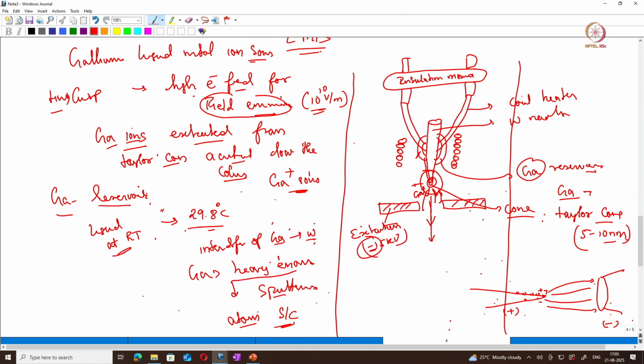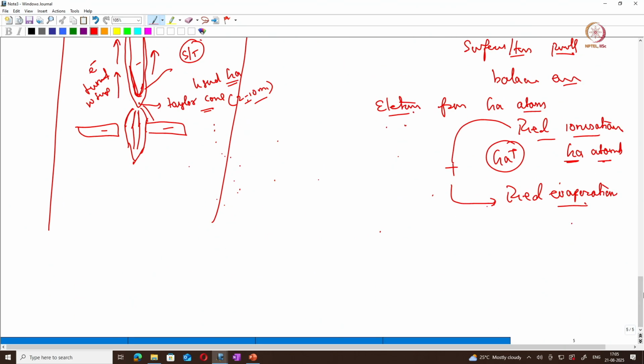And the extraction of gallium ions is a mixture of two basic principles, which are called field ionization and field evaporation. Field ionization is by the tunneling of electrons towards the tungsten tip, which makes the formation of the Taylor cone of gallium plus ions, and due to the electric field and the extractor, these gallium ions get field evaporated from the liquid and accelerate towards the column, towards the specimen surface.